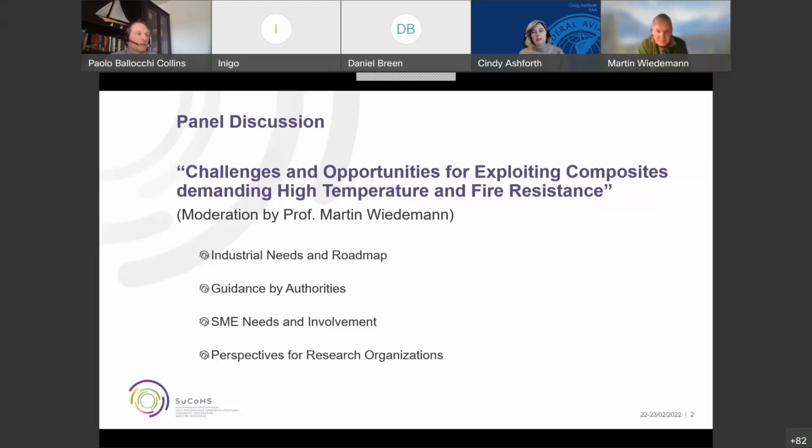So I can answer your question, Cindy, if you want. So what are we going to use those values for? The answer is, we're using it two ways. In the ARP 6337, the values are requested to assess your knockdown values due to material variability factor, and that affects, as you said, not the dynamic, but the static loads. So that's the first application. But the second one is the one that goes straight into material specification. So the values that we refer to during the qualification of the material are the values of the B-basis or the A-basis.